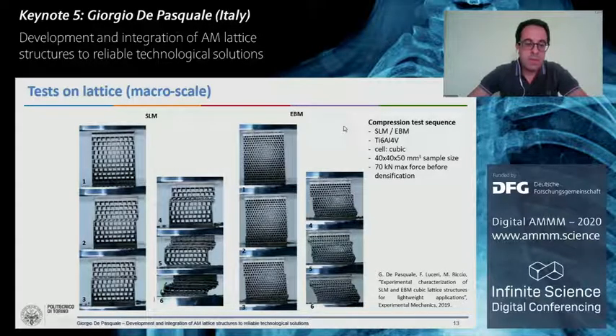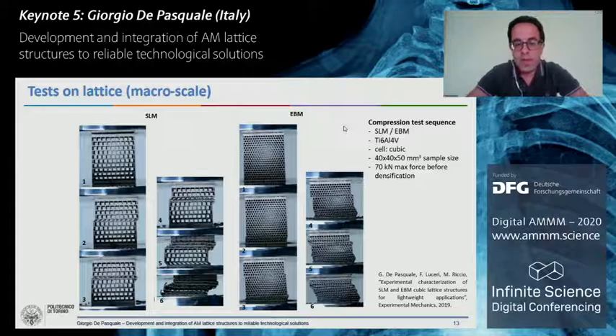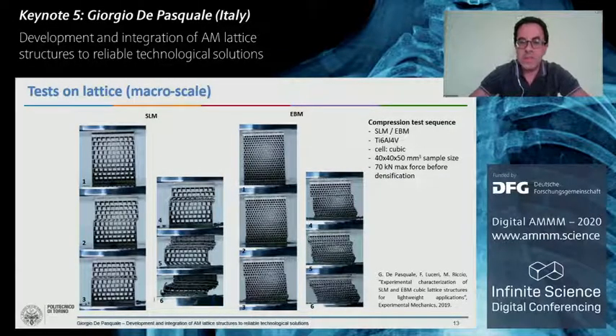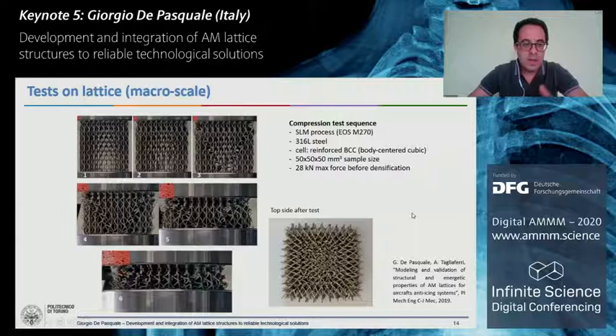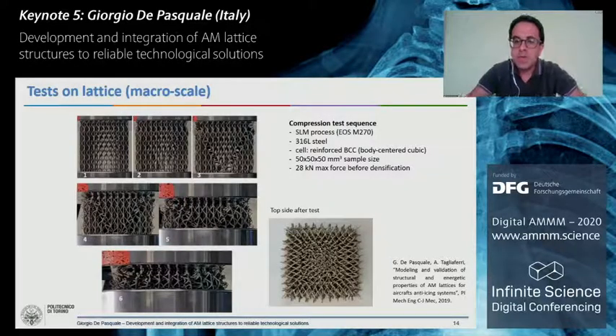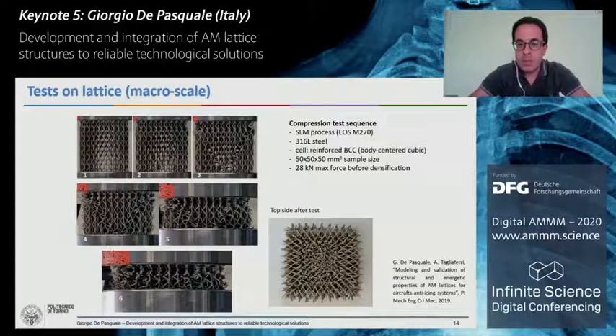Here again, we have collected some frames of our compressive tests on cubic cells in titanium alloy. This is a sample represented by a cube, a 40, 50 cubic millimeter sample. The maximum force applied is 70,000 Newton of compression, so a pretty high force. Another example of another kind of lattice structure: here we have a BCC cell, body-centered cubic cell, in steel. The same shape of the sample again, 50 by 50 by 50 cubic millimeters.